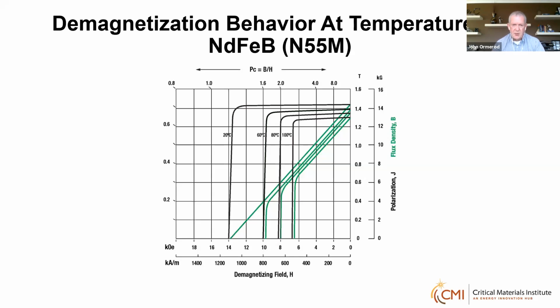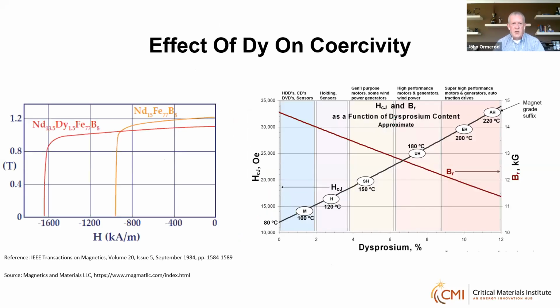If these magnets are subject to high demagnetizing fields at startup or where high torque is required, depending on the design, it's highly likely that the magnets will be permanently demagnetized, and of course lead to the loss of motor performance. Now, it was known from the very early days of neodymium-iron-boron development that the substitution of certain heavy rare earth elements improved coercivity.